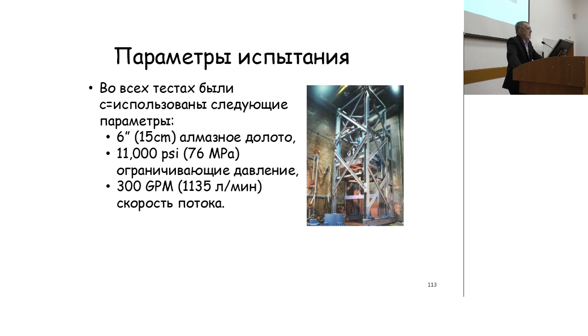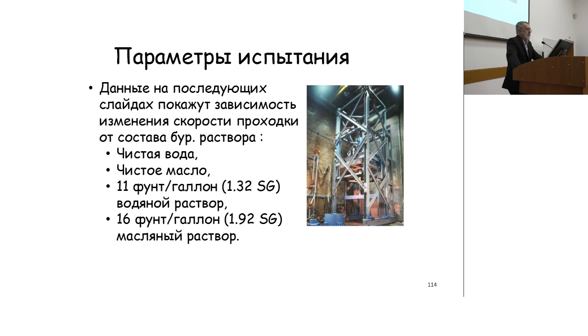They did many tests, and I'm only going to show you some of them here. In all the tests I'm going to show you, the bit is a 15 centimeter bit. The confining pressure, that would be the borehole pressure around the rock, is on the order of 76 megapascal, and the flow rate is shown there. The bit, the pressure, and the flow rate are all the same. What they're going to change is that they're going to use just clear water for a drilling fluid, and then a clear base oil for a mud, and then a weighted mud, a 1.32 specific gravity mud.